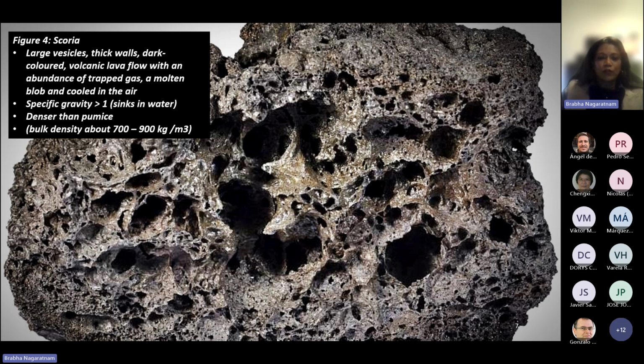And so it looks like a molten blob because it comes from the volcanic lava, and it's cooled in air. The specific gravity is more than 1, so definitely this type of aggregate will sink in water. It's denser than pumice. Like I said, the walls are thick, so much thicker than pumice, which has a very light kind of skin on it. The bulk density is higher than pumice, at 700 to 900 kilograms per cubic meter.